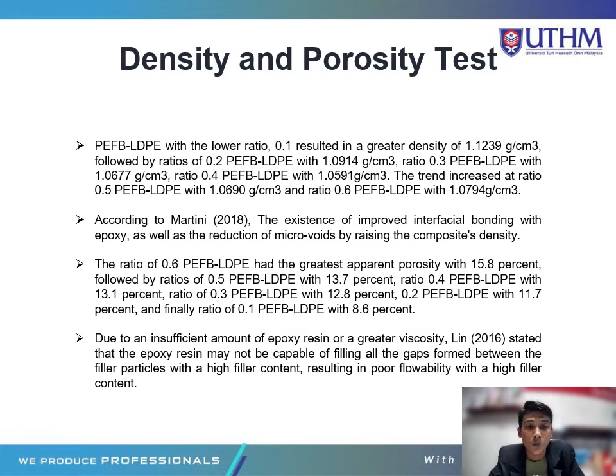Okay, PEFB with the lower ratio 0.1 resulted in the greatest density of 1.1239, followed by ratio 0.2 with 1.0914, ratio 0.3 with 1.0677, ratio 0.4 with 1.0591. The trend increased at ratio 0.5 with 1.0690 and ratio 0.6 with 1.0794. According to Martini 2018, the existence of improved interfacial bonding with epoxy, as well as the reduction of microvoids, raises the composite density.